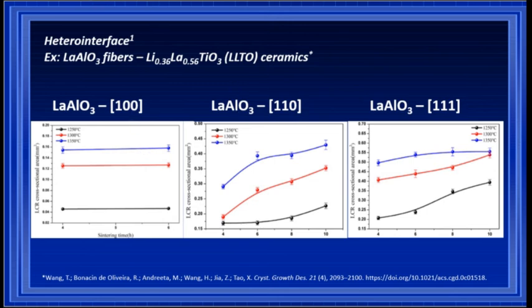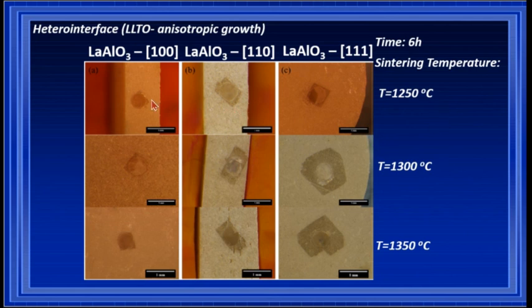However, when we use the 110, we can see that by increasing the sintering time, there is also an increase in the area of the LCR region. The same for 111. When we look at the optical photograph, we can see what we already said, that for higher sintering temperatures we get larger crystals, but with the 100 orientation we got very small crystals on the side of the fiber. And one very interesting feature is that when we use 110, we get a very anisotropic growth along the side of the fiber.